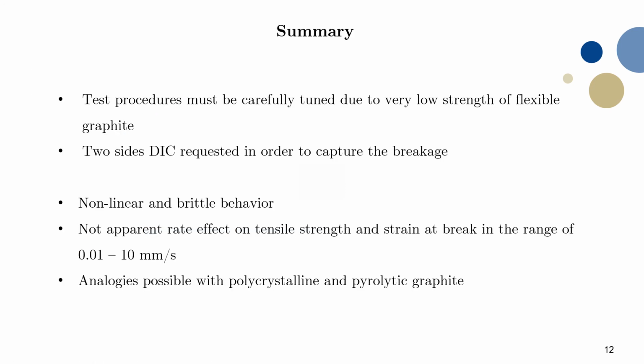So as a summary, we can say that the test procedure for Sigraflex flexible graphite must be carefully tuned because of the low strength of this material, especially in the in-plane directions, and it's also hard to capture the first location of the fracture. And about the stress strain curve, it is nonlinear in all the strain domain, and it has brittle behavior, but no apparent rate effect is visible on the strength and strain at break up to 10 millimeters per second. As a starting point for future modeling, it is important to notice that some analogies would be possible with other forms of graphite, such as polycrystalline and pyrolytic graphite.